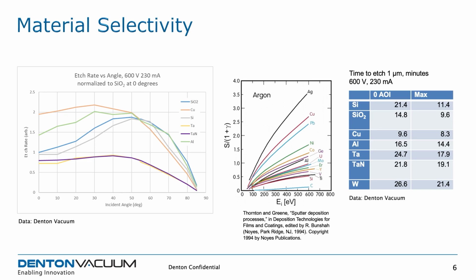On the right is kind of typical etch rates. So 600 volts and 230 milliamps is not the highest power the machine can go to, but it's on the higher end, but it's a comfortable level where it's very reliable. So in that case, we're getting etch rates of a micron of etch in around 8 to 20 minutes, depending on the angle and the material. So that means you can also do stuff like etching chips through the backside. You can go through 20 microns of material in a reasonable time.